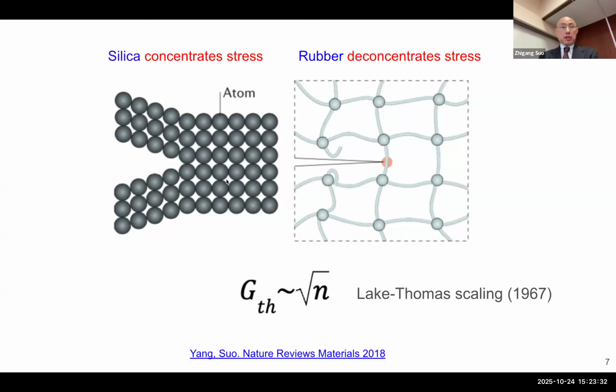Just any rubber is tougher than glass, right? So many years ago, this famous model, the Lake-Thomas model, found a scaling. The threshold, the fatigue threshold under cyclic loading, scales with the square root of N. N is the number of repeat units along the strand.